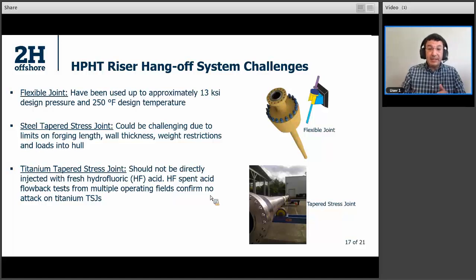One limitation is that titanium can be susceptible to acid. If you are using the titanium tapered stress joint, you cannot acidize your wells directly through the production flow lines. So that's one of the limitations for the titanium tapered stress joint.